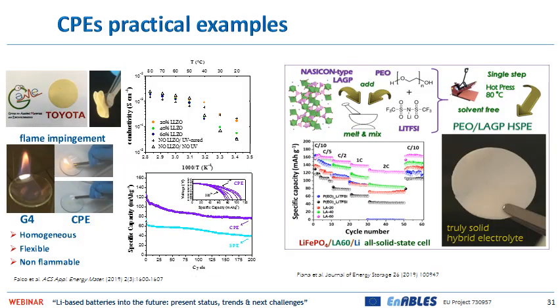Most of the systems studied recently involve inert ceramic particles and PEO with the possible addition of lithium salt. For example, by incorporating LLZO, we were able to fabricate mechanically robust composite electrolytes with ionic conductivity approaching 10^-4 Siemens per centimeter at ambient temperature, which allowed stable cycling at ambient temperature, as well as by the use of LAGP, a NASICON-type ceramic, we obtained a huge improvement in the cycling performances compared to bare PEO-based electrolyte.